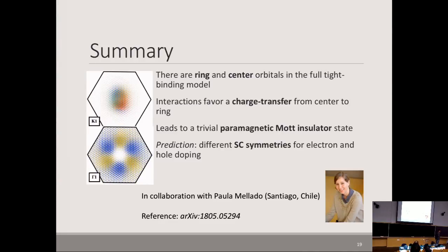So if I now mentally try to construct a Wannier function, which is what everybody should have been doing, then I can tell you that you're going to have orbitals that are very delocalized, meaning that it cannot be just well confined within this hexagon you have, because you need to be able to cancel the orbital at a certain momentum. You need to cancel the center or the tail. So the Wannier function must be way bigger than this single hexagon. Otherwise, this will never happen.